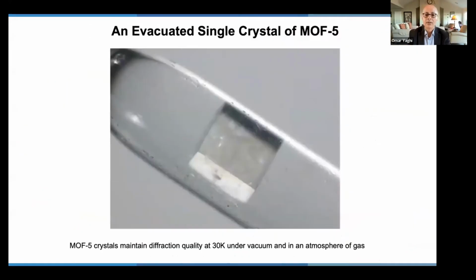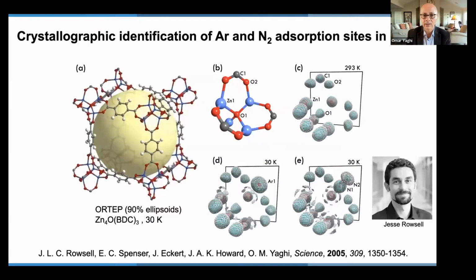So the fact that MOF 5 is architecturally robust means that we can take that crystal of MOF 5 and cool it down to 30 Kelvin and look at where the gas molecules are residing in the structure. Find out, indeed, if our vision of every atom being a surface is realized. And so that's the experiment that we did. Take that crystal, cool it down to 30 Kelvin. Fortunately, the crystals don't crack. They don't lose their crystallinity. And here's the first time ever that someone could find the crystal structure of a large pore material without anything in the pore. And you can see that as you introduce argon or nitrogen,